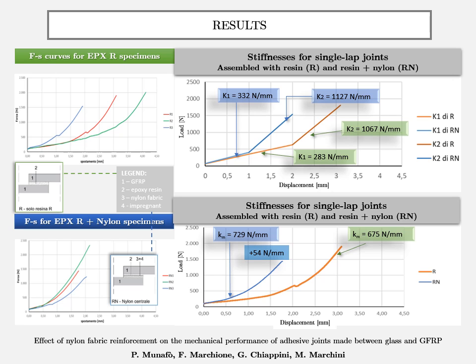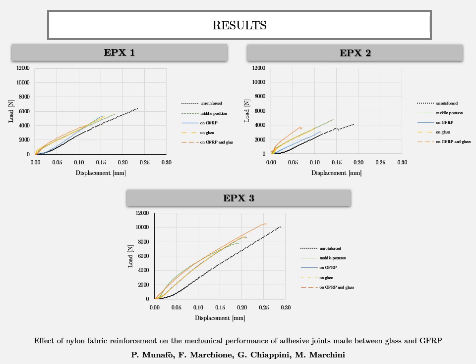The comparison with the obtained results showed the effective contribution of nylon in the joints bonded with epoxy resin, with an increase in stiffness of 54 Newton per millimeter. As for the failure mode of the specimens, it is the light fiber tear failure mode, with the defibration of the GFRP at the bonded interface.